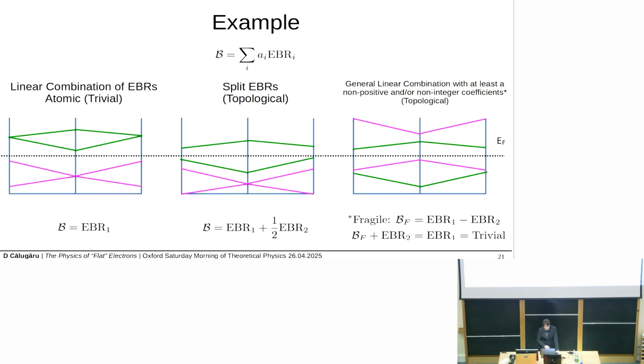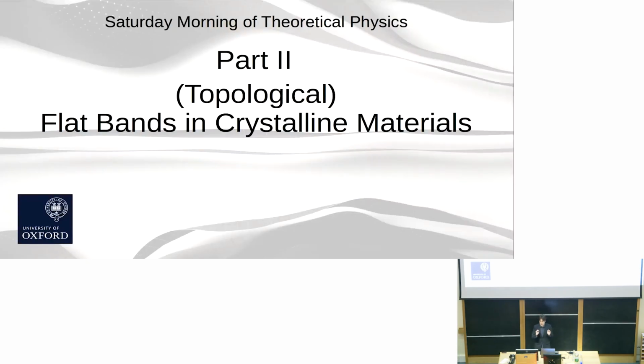In the middle, you have a case where the bands decompose into a fraction, a rational non-integer combination of elementary band representations. By definition, in such a case, your bands are topological. They do not admit a localized real space description. And of course, you can have other situations where the bands are an integer linear combination, but one of the coefficients is negative. I will not go into the details, but those are also topologically non-trivial. So the main takeaway of that section was that a band is topological if it doesn't have an exponentially localized real space description.